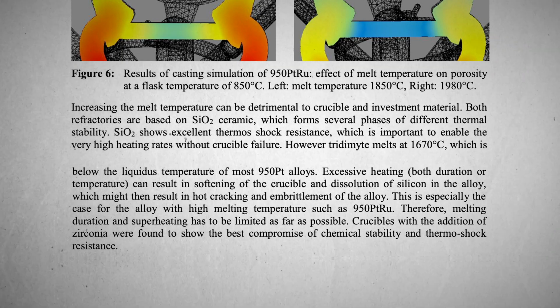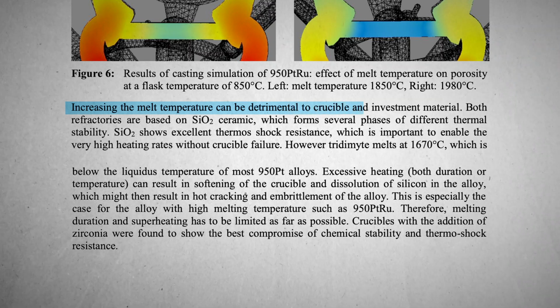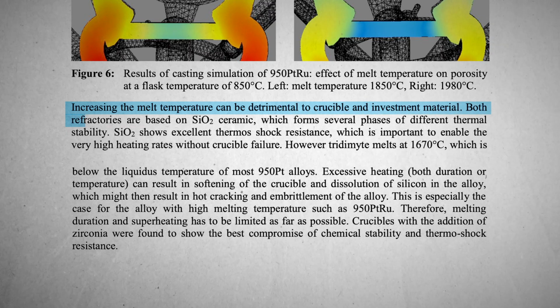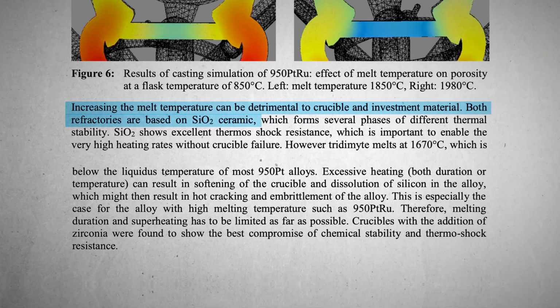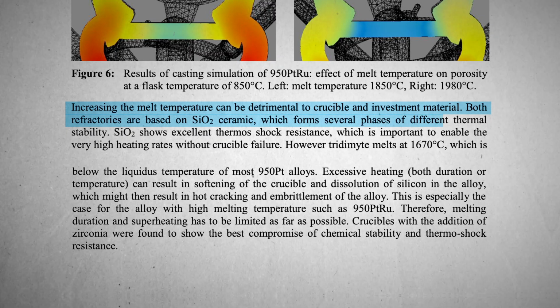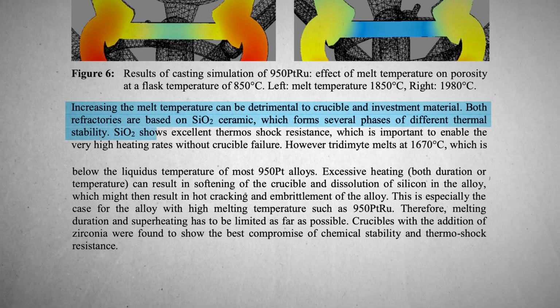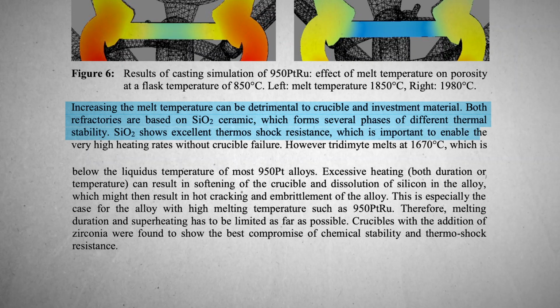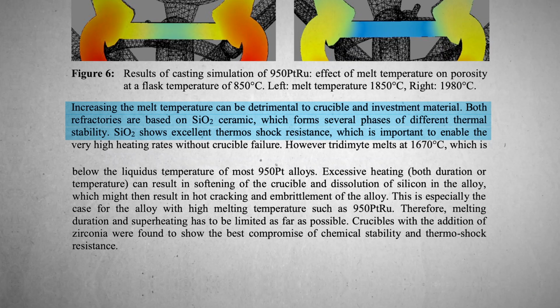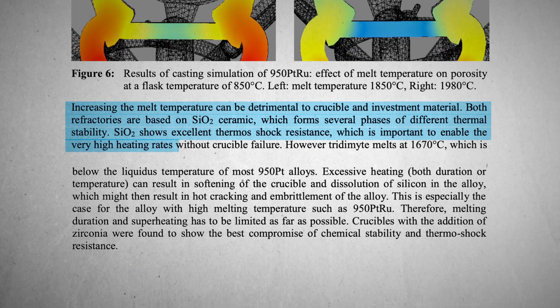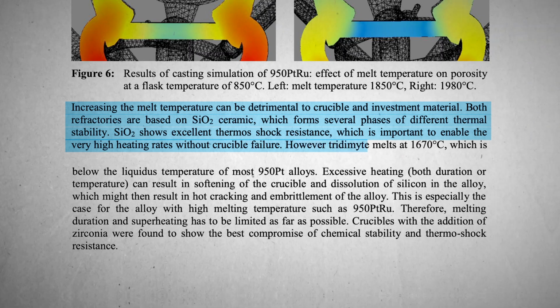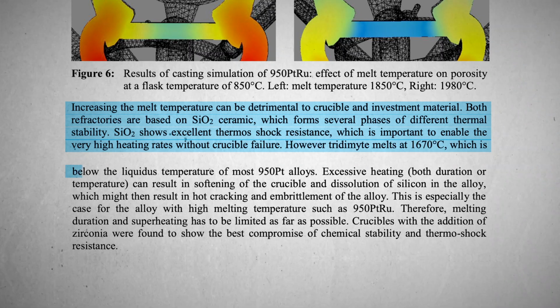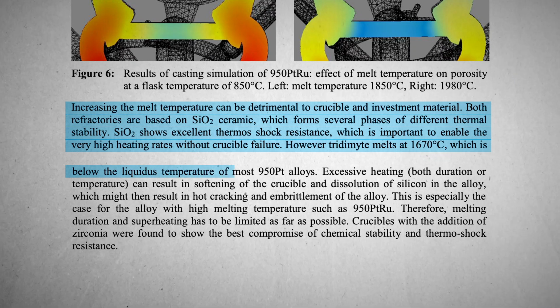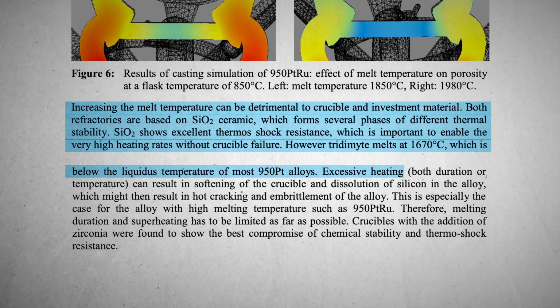Quoting directly from the paper, "Increasing the melt temperature can be detrimental to crucible and investment material. Both refractories are based on silicon dioxide ceramic, which is silica, which forms several phases of different thermal stability. Silicon dioxide shows excellent thermal shock resistance, which is important to enable the very high heating rates without crucible failure. However, tridymite melts at 1670 Celsius, which is below the liquidus temperature of most 950 platinum alloys.